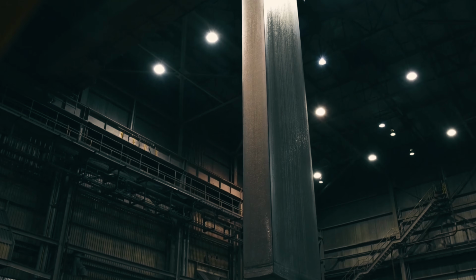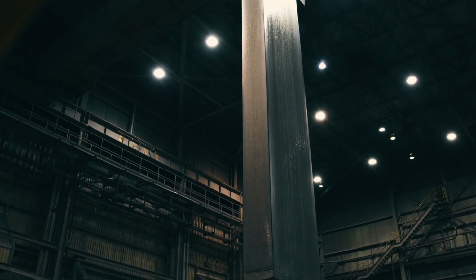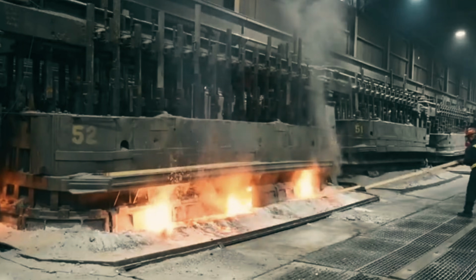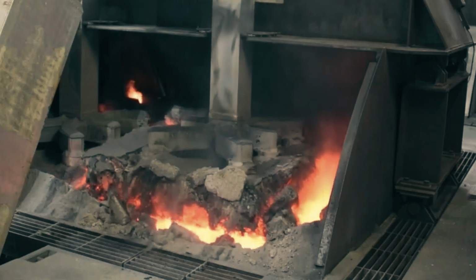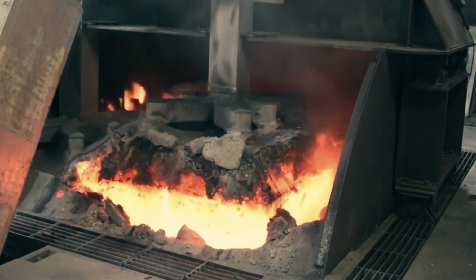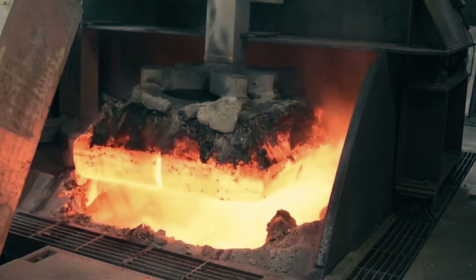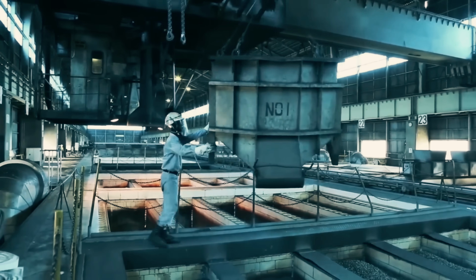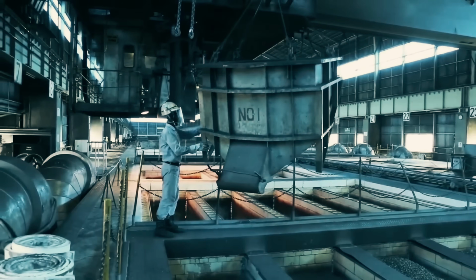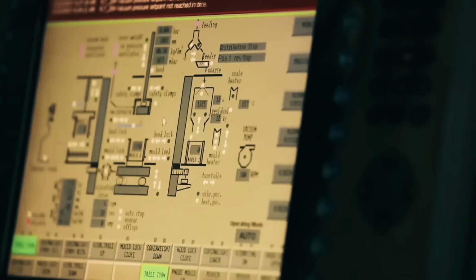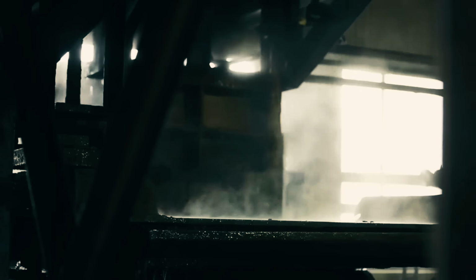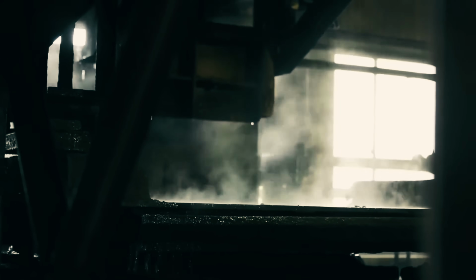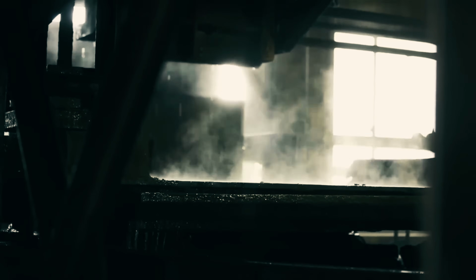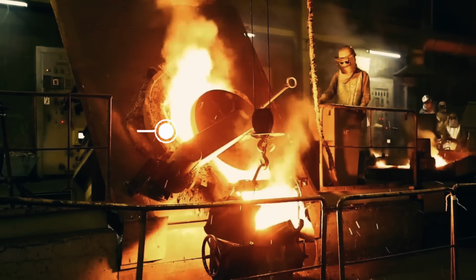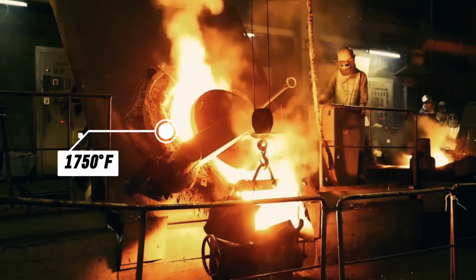The alumina still isn't metal. It's an oxide bound tightly to oxygen atoms at the molecular level, and that bond is stubborn. To break it, the alumina is dissolved into a molten bath of cryolite inside massive carbon-lined steel tanks called reduction cells, or pots. Each pot is then blasted with electricity, hundreds of thousands of amps, running between carbon electrodes submerged in the molten mixture at temperatures near 1,750 degrees Fahrenheit.